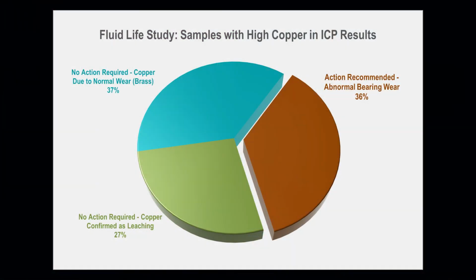Right. So basically, if you're seeing a lot of high copper, you could be assuming that it is copper leaching. But if it triggers an SEM, you could then dive deeper and find out what's going on. Absolutely. We did a study where we determined that in one third of the instances where we were seeing leached copper, there was also the presence of abnormal bearing wear. Of course, that was varying degrees. Any bearing wear is typically considered abnormal, but just because there's the presence doesn't mean that it's masking a failure. But there are many instances where it is masking a failure.